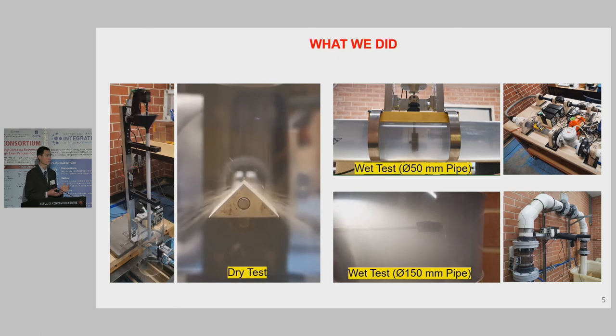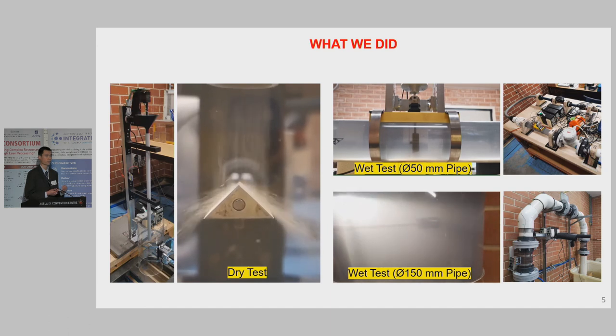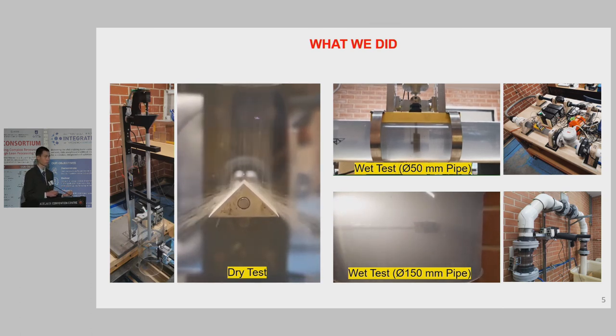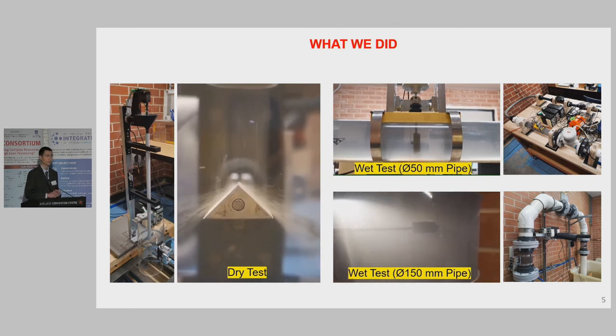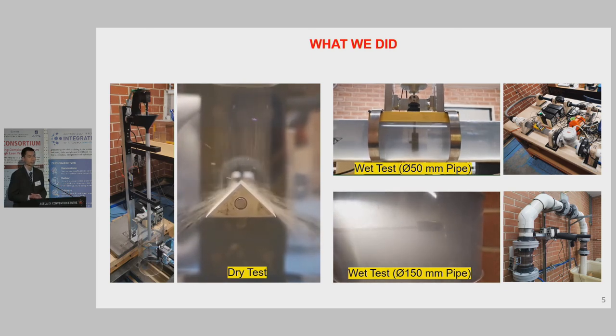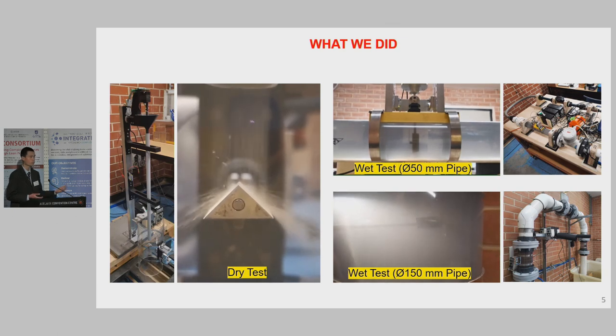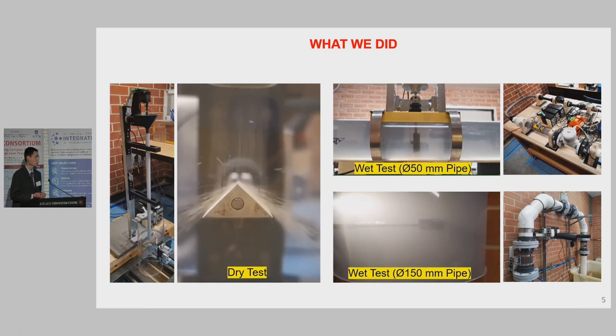To understand the particle probe impact mechanism, we have done dry tests in the air using sand in free fall from a certain height. To correlate flow-induced drag with size distribution, we have also done tests with slurry on a small scale flow system using a 50 millimeter diameter testing section. Someone may ask, is it the same case on a full scale system? To answer this, we have also conducted experiments on a full scale system using a 150 millimeter diameter testing section.